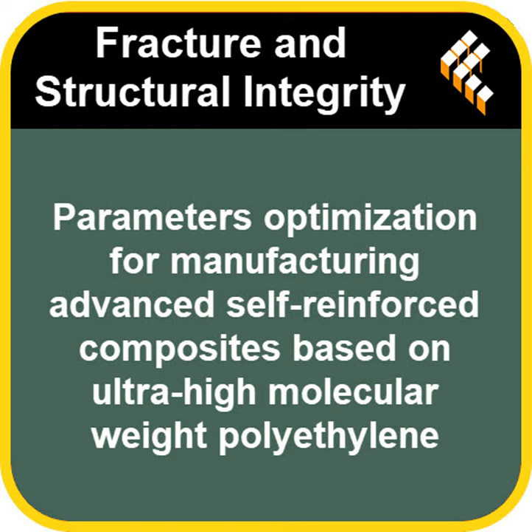Okay, so the shape helps the bonding, but you mentioned stresses earlier. The paper says this pressing generates internal stresses, and they're like a double-edged sword. Precisely. On the one hand, these leftover or residual stresses can actually be good. They push the fibers together, increasing that contact pressure, which helps transfer load efficiently when you pull or bend the material. Makes it stronger, basically. Up to a point, yes. And the results support this. They found peak strengths, like 11.1 MPa for shear and 130 MPa for bending at those optimal mid-range temperatures around 165, 170 degrees C.